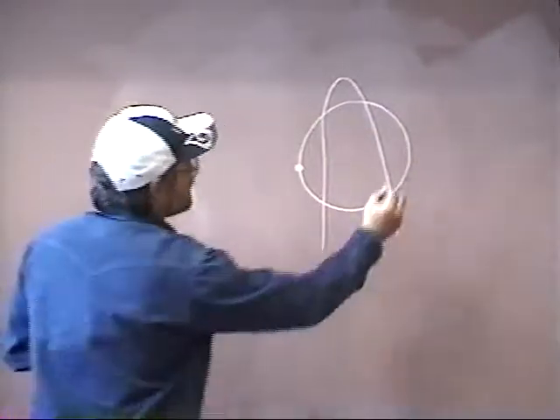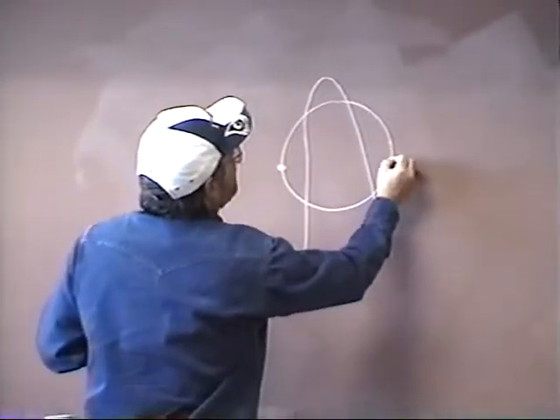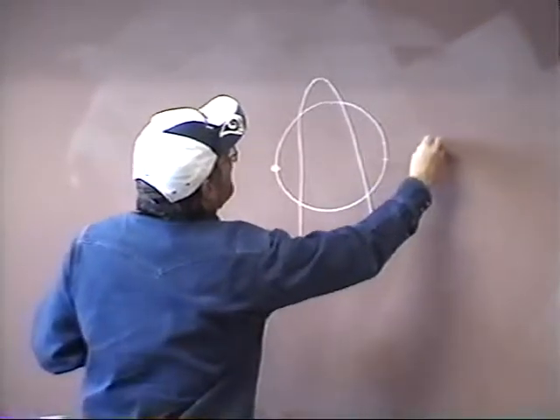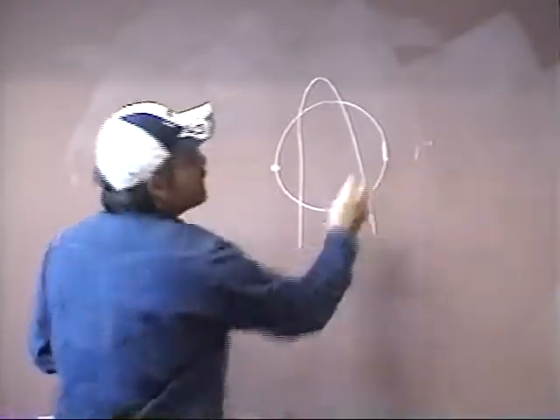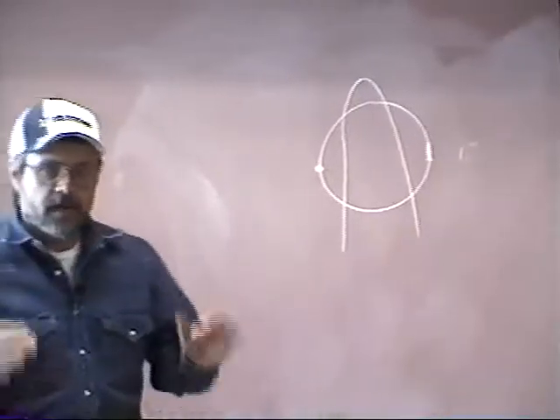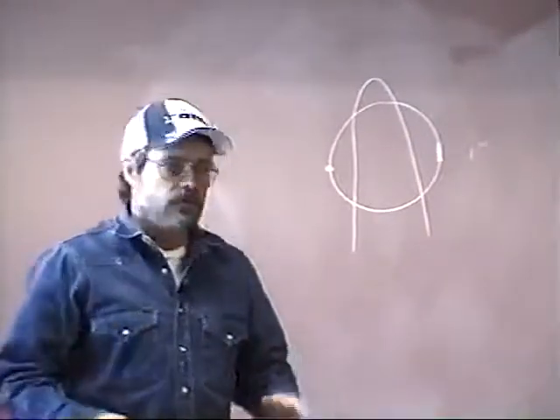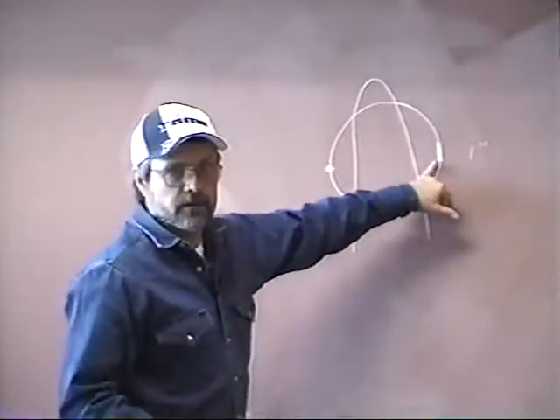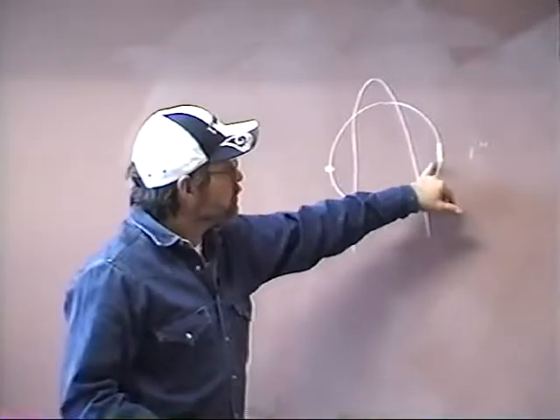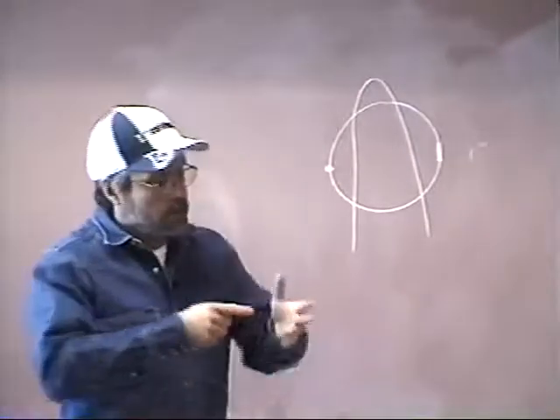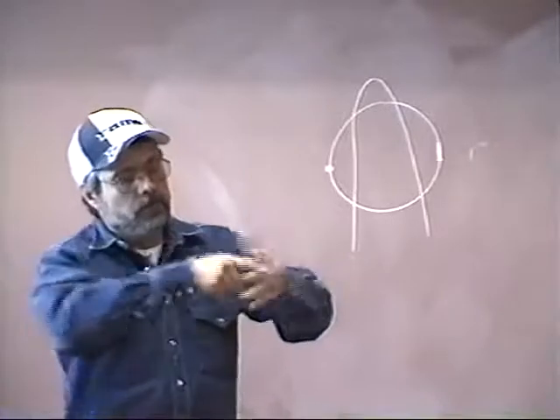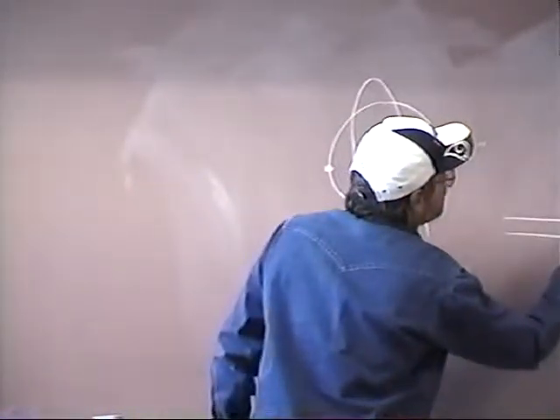Now when we put the second tack in, we're going to come directly opposite, and we're going to make a 1-inch tack right here. Bear in mind, the tack becomes part of the weld, so you want to have full penetration on there. Not only do you want to have full penetration, but when you get to the end of that tack, you want to poke that welding rod through to open up the keyhole. So it's looking like this when you're done.